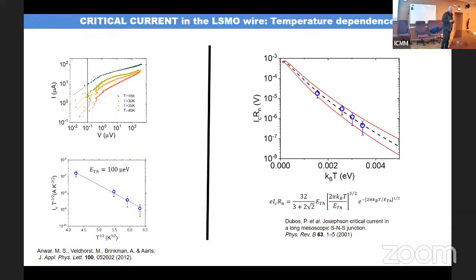the Likharev theory or de Gennes theory that you may know, for superconducting normal superconducting weak links. And we got reasonable agreement with the prediction of this theory. That may not necessarily be the case, because this is for normal metal weak links, and we have, of course, singlet superconductivity, and here we have triplet superconductivity in a ferromagnet. But still, we got reasonable agreement with the theory, and somehow we were relieved, because one expects that equal spin triplets in a ferromagnet should behave similarly to singlet pairs in a normal metal. This is the idea.